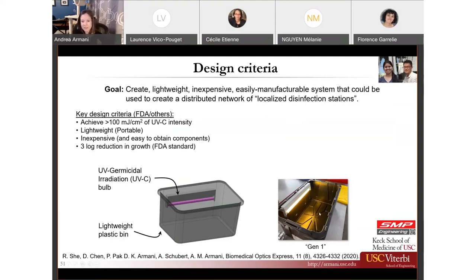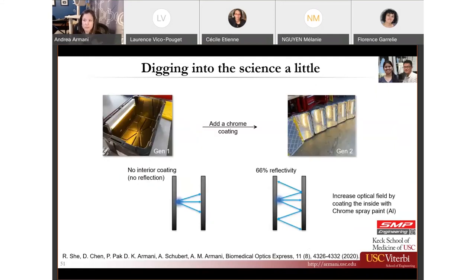So the black is obviously very absorbing. One super simple improvement is to coat the inside with a very reflective coating. When you think about what materials to coat with, you want something that's reflective for UVC light. Aluminum is very highly reflective in the UVC wavelength range, and chrome spray paint is primarily aluminum. So we used chrome spray paint to get that super smooth aluminum coating. Effectively, this creates a Fabry-Perot type cavity.